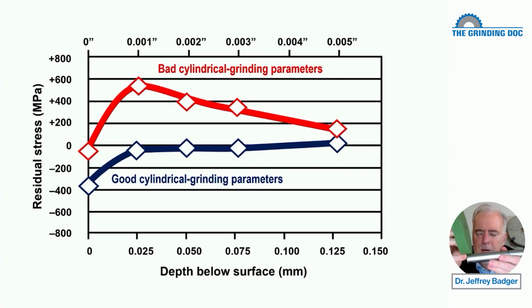Now I talk about this a lot more in my course. I'm going to run through it here quickly, but what they were doing is they were taking a deep cut with a really fast workpiece RPM, something like 300 RPM. And so what happened is only a tiny sliver of the wheel is doing all the work. Their overlap ratio was some crazy number like 54. And I like overlap ratios in roughing of 1.2. 54 is a lot bigger than 1.2. And that was the other major problem they had. So they were asking a thin sliver to do all the work.